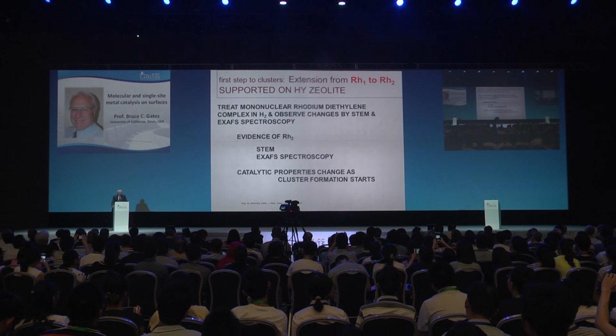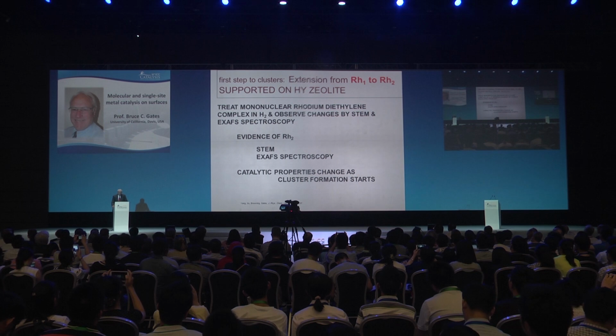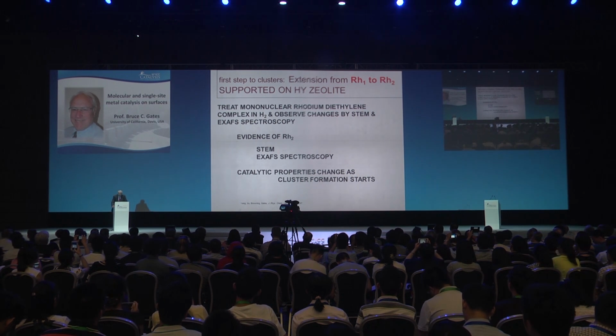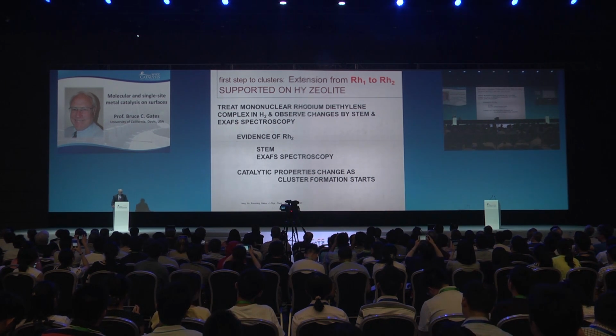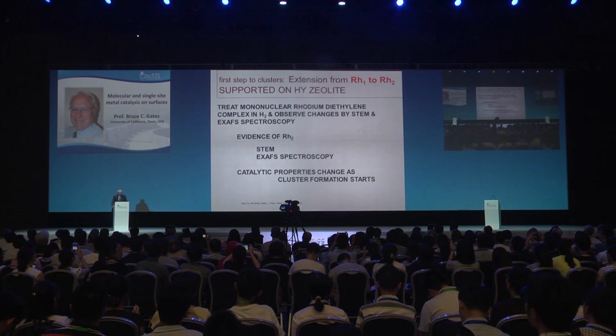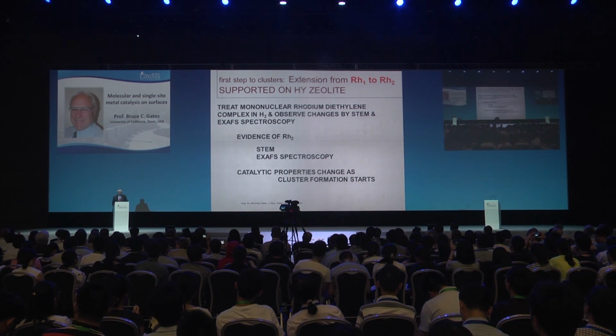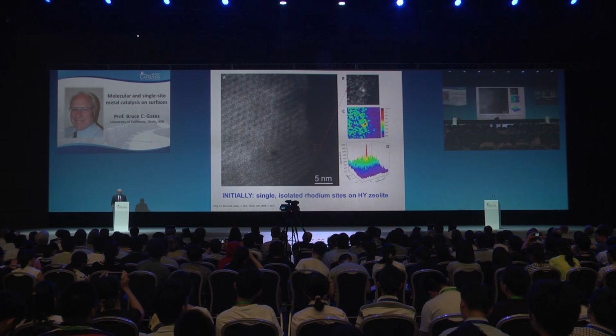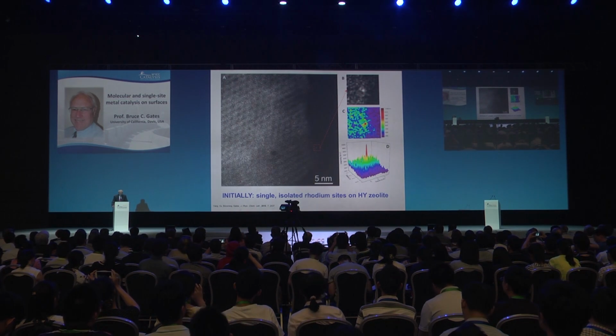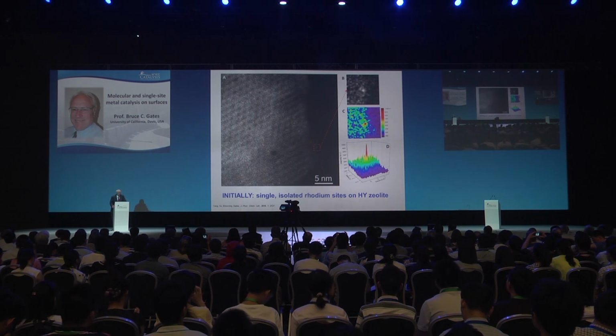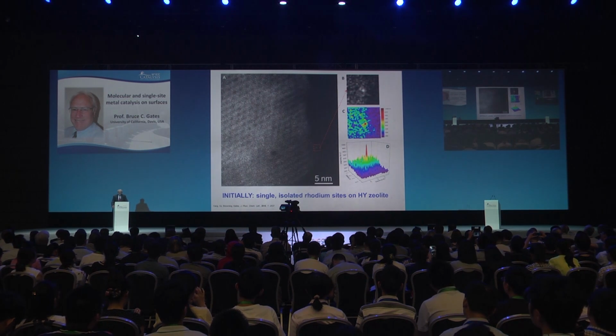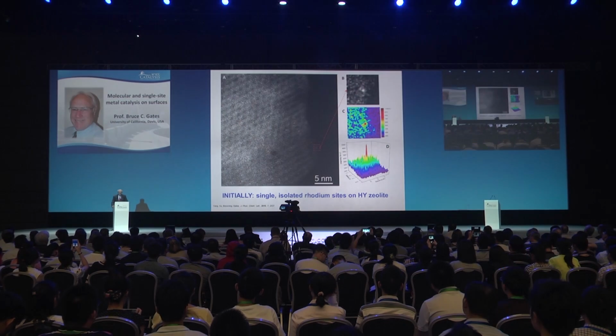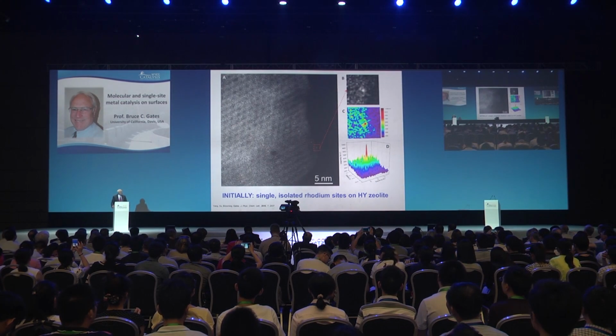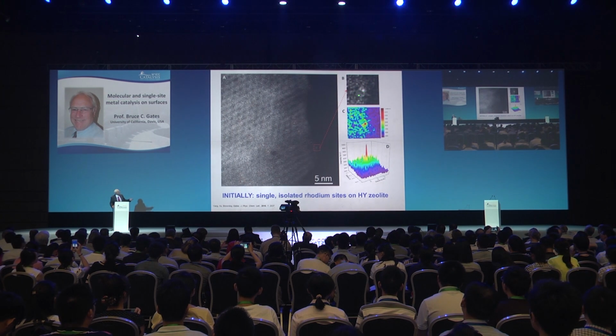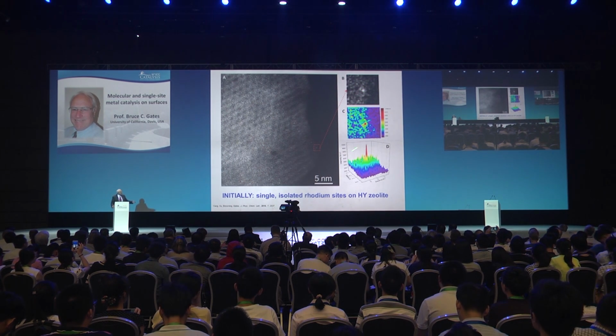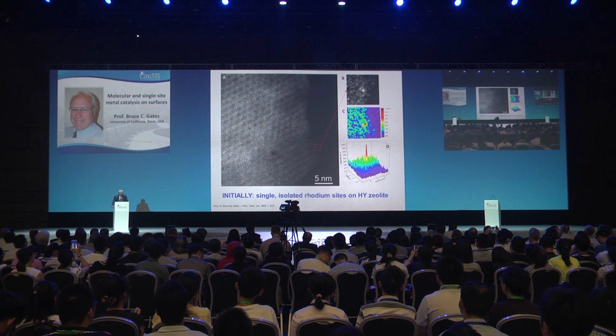We start with mononuclear rhodium complexes on the zeolite, essentially the prototypical catalyst we've talked about, now with rhodium as the metal, and characterize it by microscopy and XAFS spectroscopy. What do we see initially? All the rhodium is site isolated - it's mononuclear rhodium. We've blown up one part of the image to show the rhodium, and done intensity analysis to show that's an isolated rhodium center. That's what we have initially.